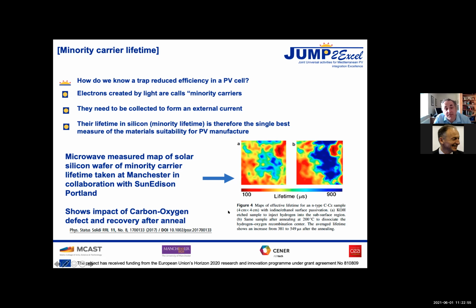And the way of measuring minority carrier lifetime, in our lab, we use a microwave process. So we have a mapper that illuminates a region of the cell with a pulse of light, and then a microwave pulse is sent in, it's reflected from the cell, and the reflectivity of the silicon depends on how many minority carriers there are. So we get a decay, and we can measure the lifetime of the minority carrier, and we can map that. So this is a 4 centimeter by 4 centimeter region of Sun Edison solar silicon, and the lifetime is here. And you can see that on the left-hand side here, it's mostly red. So the lifetime has shortened, and the average lifetime is less than it should be.